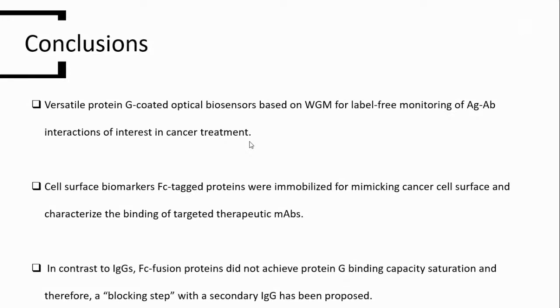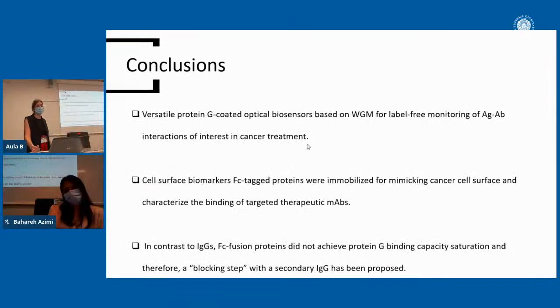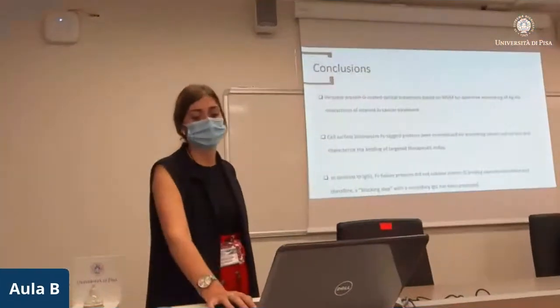Apart from antibodies, we have also immobilized cell surface biomarkers for mimicking somehow the cell surface and characterizing the binding of targeted monoclonal antibodies. This study has been performed with already existing monoclonal antibodies, but the idea is to apply these proof of concept sensors to validate the targeting of novel formulations. And this will be done in the future. And something that we found is that, in contrast to standard IgGs, Fc fusion proteins, even though they contain the same Fc fragment from IgG1, cannot saturate the protein G binding capacity, and therefore we try to overcome this limitation by introducing a blocking step with an extra secondary IgG.